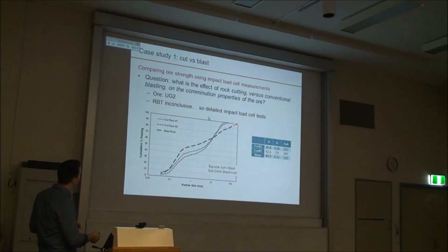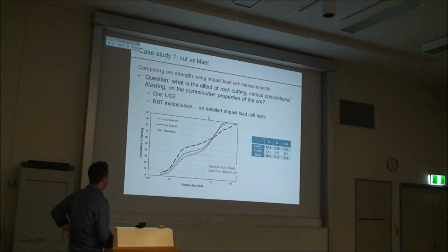This is the blasted rock, so it has a coarser size because the blast is not selective. The cut rock has a much smaller top size, because of the cutting mechanism you can control the top size produced. But interestingly, the blasted rock in the fine end, down to minus 1 millimeter, was actually finer. So this says that the blasting produced a little bit more fines compared to the rock cutting machine.